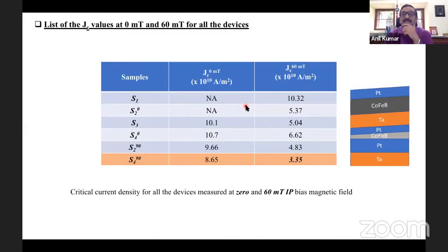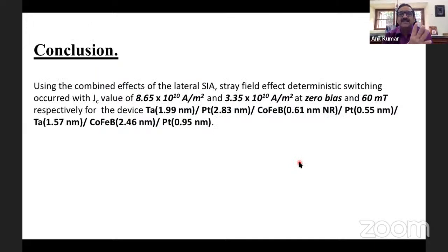Now, what do we achieve with this kind of structure so far? Look at the last curve here. We are now able to switch the magnetization at a current density of 3.35 times 10 to the power 10. Imagine the first transparency I showed you, 5 times 10 to the power 11, 3 times 10 to the power 11, now 3 times 10 to the power 10. One order of magnitude reduction in the current, and 2 orders of magnitude reduction in the current with respect to spin transfer torque. So this is the improvement. And so what we achieved so far is 3.35 times 10 to the power 10 here.